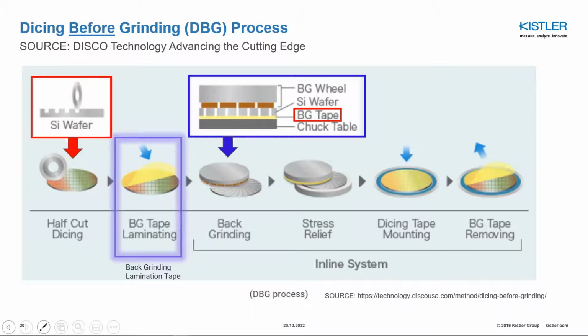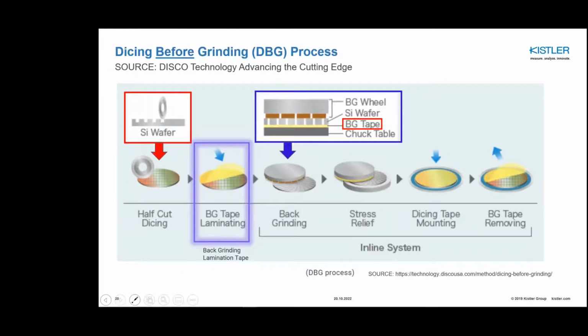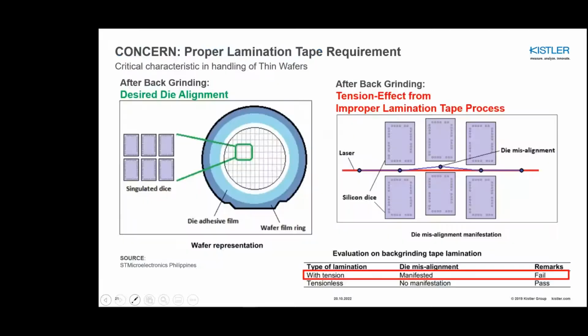In the next slide, we will examine how the earlier process step of lamination influences a later process result with the individual dies. On the left, the wafer is represented and each die is equally spaced after grinding. This is the desired die alignment result. On the right, the tension from the back grinding tape is released, causing the dies to be misaligned after the back grinding process. The root cause is noted in improper lamination tape process.